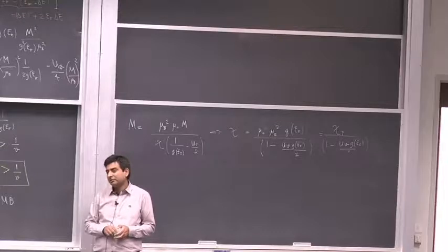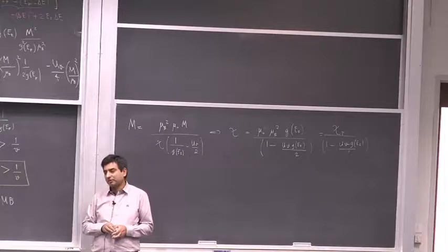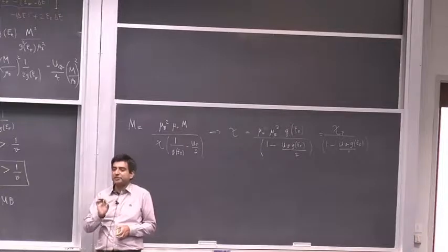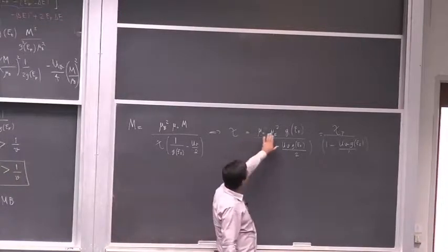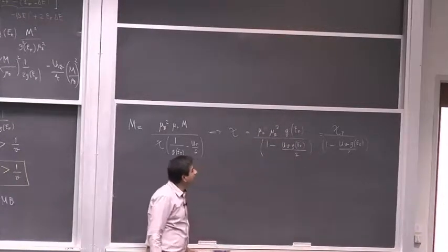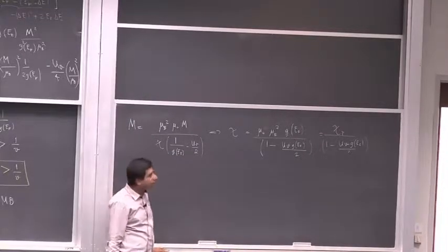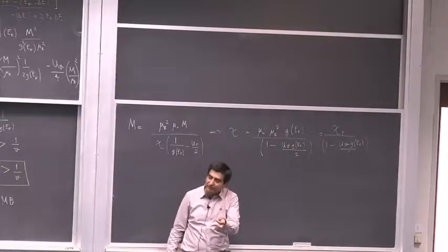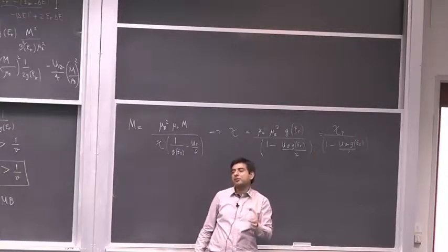Sorry? You can build temperature dependence into the Hubbard model, but the Hubbard model basically adds a Coulombic repulsion term which is temperature independent. So the susceptibility here for a Pauli paramagnet is independent of the temperature to first order. It only depends upon the fact that the density of states is dependent on the Fermi level. The Fermi level has a T squared dependence on the temperature. So the temperature dependence is really small for those Pauli paramagnets.